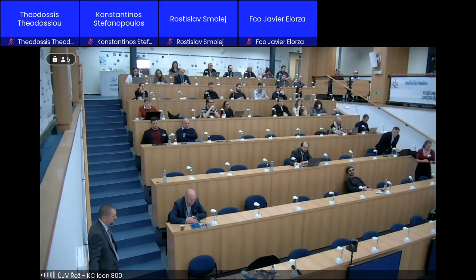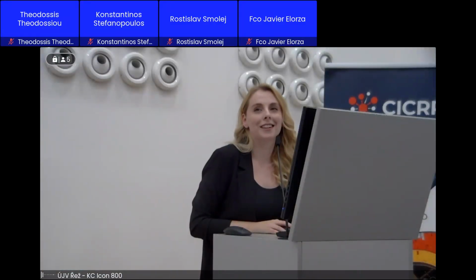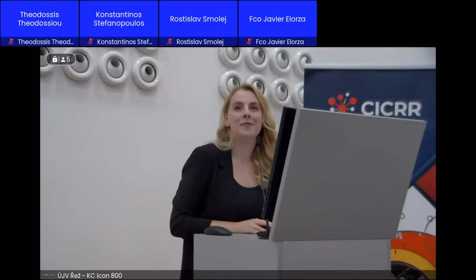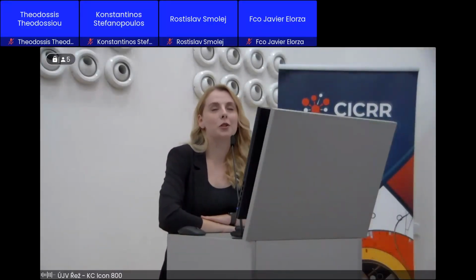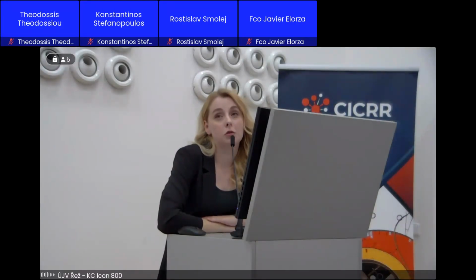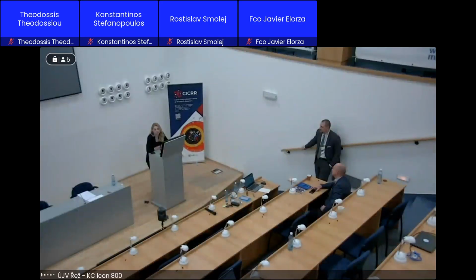So the comparison would be really simple. The VR1 is a 100-watt reactor and the LVR15 is a megawatt reactor. For us, the most important parameter is the neutron flux at the sample position, so how many neutrons you have at your sample. We have 10 to the 4 at the VR1 with an exposure time around 10 minutes, and it's very grainy and very noisy. You can still see an image, but it's very noisy. Here at this reactor, we have a neutron flux at the sample position around 10 to the 7. So 3 orders of magnitude different.